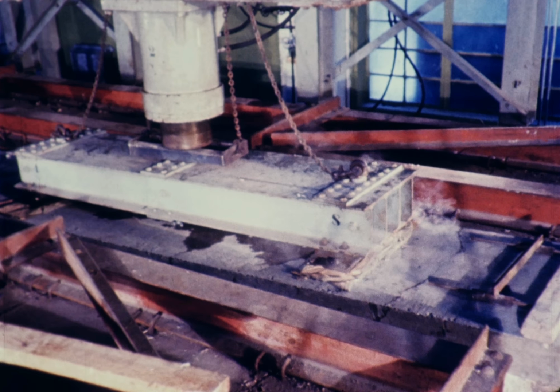We will now see 3 typical tests. First, a beam made with gravel aggregate without any supplementary reinforcement. The concrete began to spall away from the surface early in the test, eventually leaving very little cover to the steel reinforcement. The steel soon became hot. After an hour and a quarter, it reached a temperature of 400 degrees centigrade. After only an hour and a half, the beam failed.